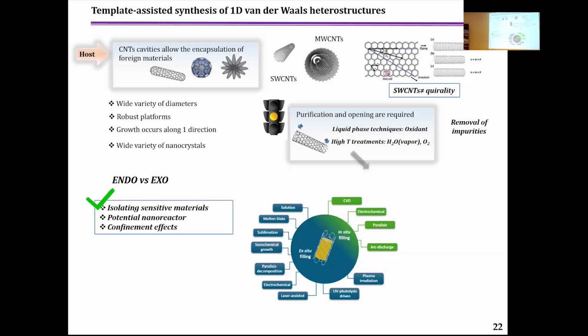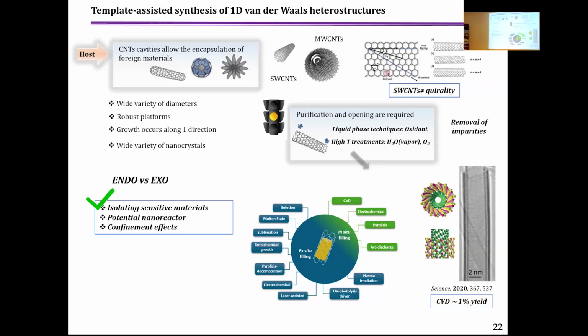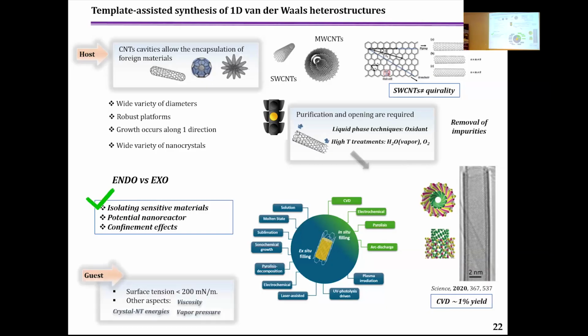So usually this endohedral functionalization is done by ex situ and in situ filling. There are some reports, but in this case, filling yields are very low, in which the author tried to encapsulate inorganic system, hollow inorganic system inside carbon nanotubes. So in this case, this is a report of the CVD synthesis where we introduce metal chalcogenide inside the nanotube that they only reach 1% yield. So then our approach is trying to take advantage of these properties to obtain hollow system heterostructures.